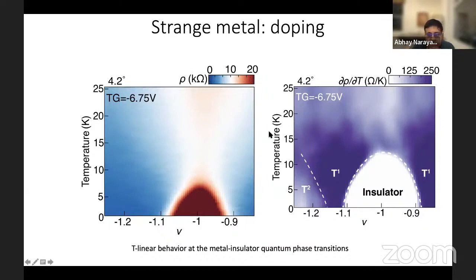And if I take a temperature derivative of this longitudinal resistance, then I can clearly see the regions of insulating behavior. These are regions where dρ/dT is negative, and that's bounded by this dashed white line here in a dome form. And at this boundary is now the metal to insulator transition.